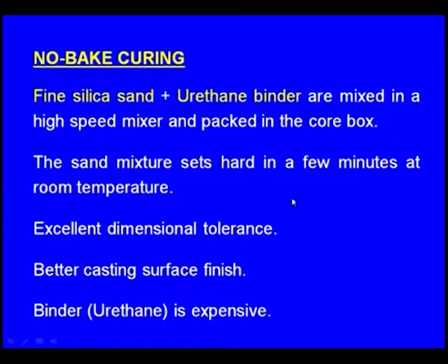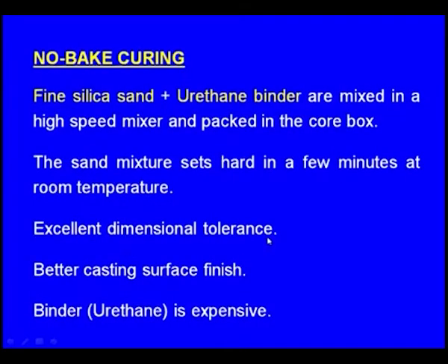Next, the sand mixture sets hard in a few minutes at room temperature. That is why, once we mix this sand inside the high speed mixer, we have to keep the core box close to the mixer, and we have to drop or shoot the sand inside the cavity of the core box, and within a few minutes that sand will be hardened even at room temperature. Next, what are the benefits of this process? We get excellent dimensional tolerance and better casting surface finish, but the only thing is this urethane binder is expensive.